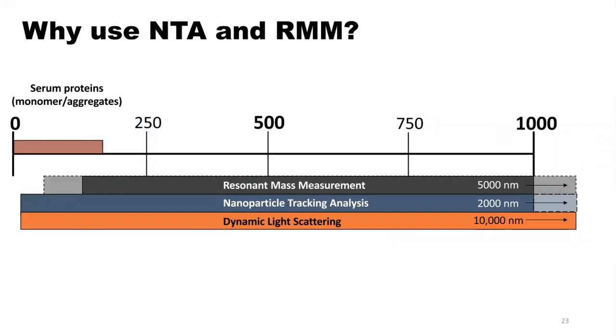So as we've said previously, we don't particularly like dynamic light scattering as a technique for doing this. But why do we have a preference for nanoparticle tracking analysis and resonant mass measurement? Here we can see with the pink bar the size of unbound protein and aggregates, but also the size limits of resonant mass measurement, nanoparticle tracking analysis, and DLS. And what we can see is how so much of the range that dynamic light scattering uses is dominated by protein, so that the DLS effectively gets confused.